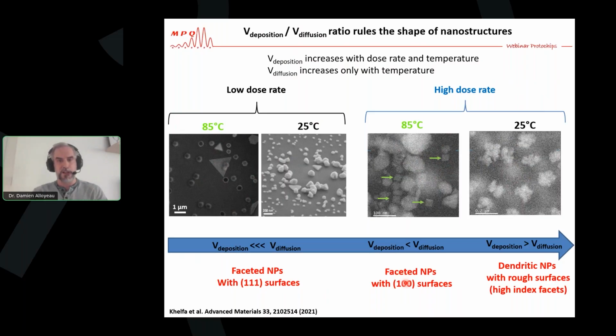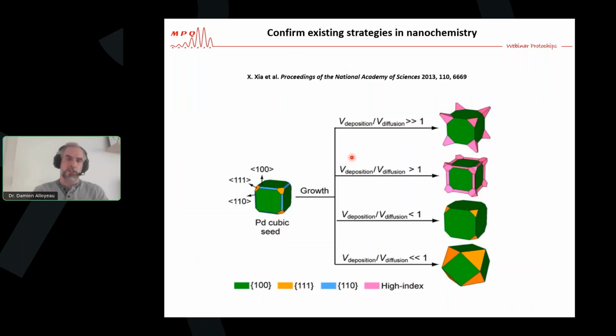And actually, this experiment perfectly illustrates the theory developed by Professor Xia at Georgia Tech University, where they have shown that starting from palladium cubic seeds, by playing with the diffusion and the deposition rate in a beaker, when you want to play with the deposition rate, you play with the redox potential or concentration of your reducing agent. And for diffusion, we play with temperature, and they have clearly demonstrated that you obtain branched morphology when you are dominated by deposition rate, and they obtain nanoparticles with 111 facets when you are dominated by diffusion rate. But in the middle, you have an intermediate regime where your cubic seed keeps growing as cubes and ends up with very nice 100 facets. So this experiment confirms existing strategies in nanochemistry.